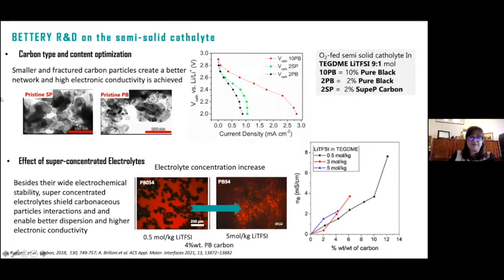We demonstrated that the carbon type and content in the semi-solid slurry is very important. Specifically, we demonstrated that smaller and fractured carbon particles create a better network, and a high electronic conductivity is achieved in the slurry. This in turn lowers the overvoltage and thus increases the discharge rate of the cell. And we also demonstrated that super concentrated electrolytes can play a role.